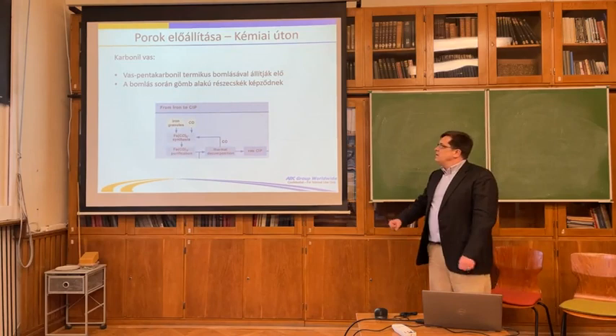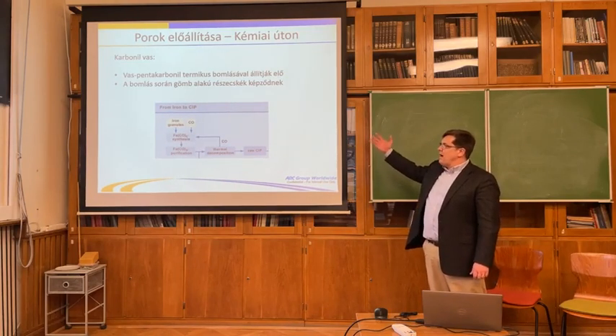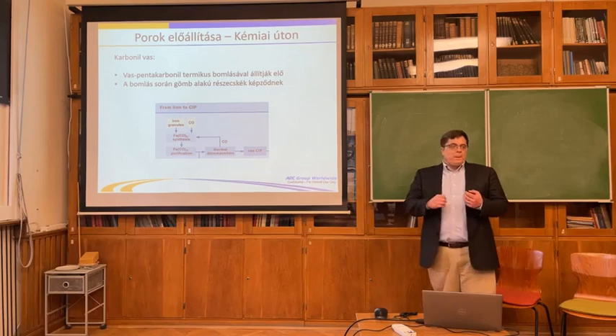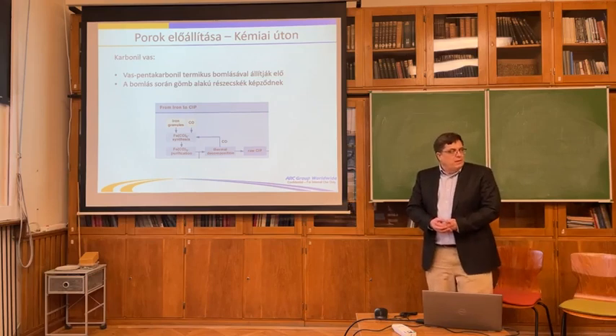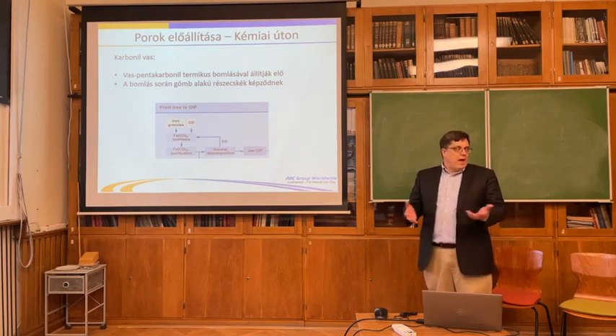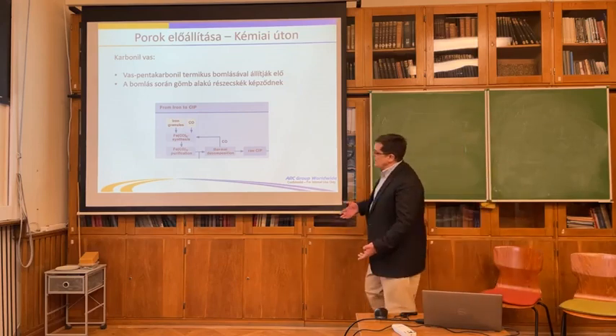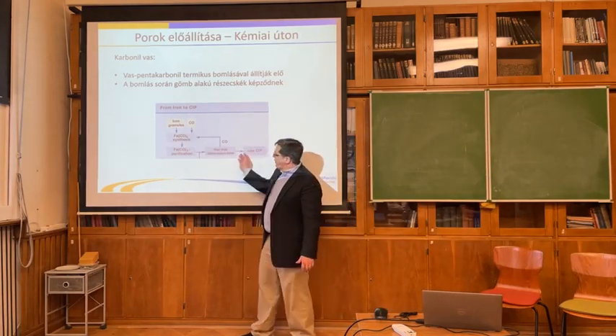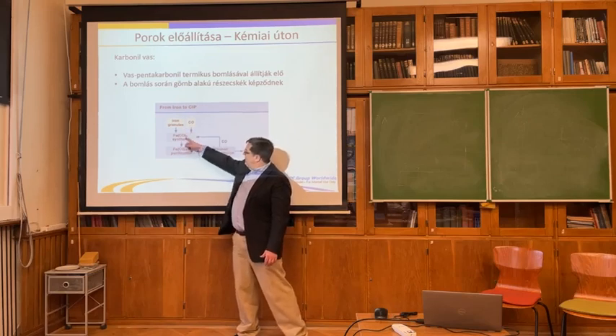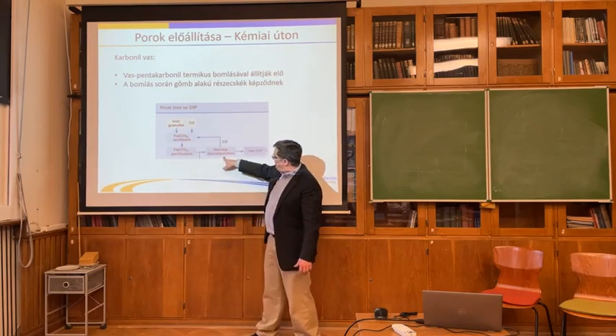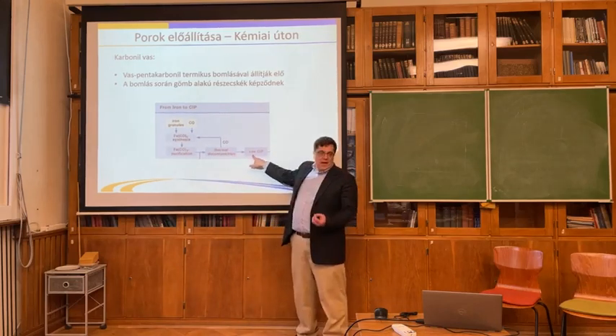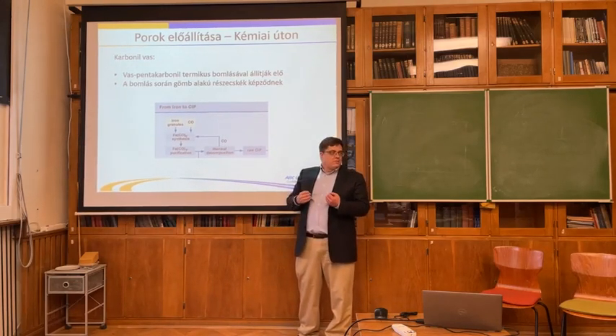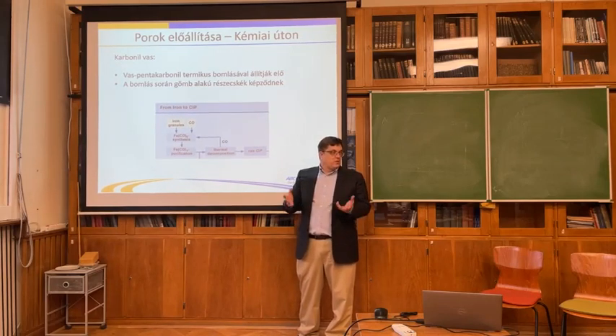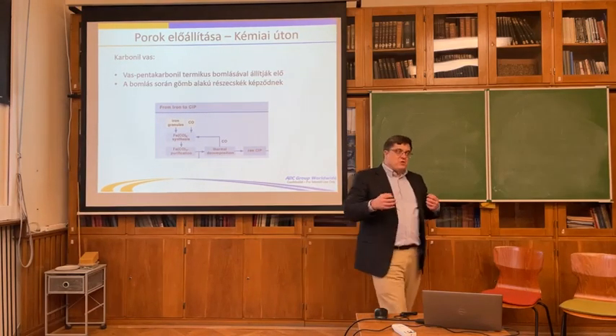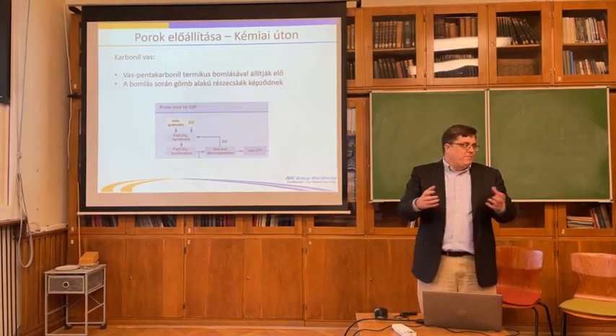The other one we do is what's called carbonyl iron powder, CIP powder. So your base material is iron powder, right? But it's not just make a melt, do an atomization, and you have your powder. It actually has to go through a little chemical process where they take their iron, combine it with carbon monoxide, and it has to decompose, but that's how they get the actual good powder, through deposition and distribution. So it's clean. If they just took the iron powder and atomized it, it would be very random.